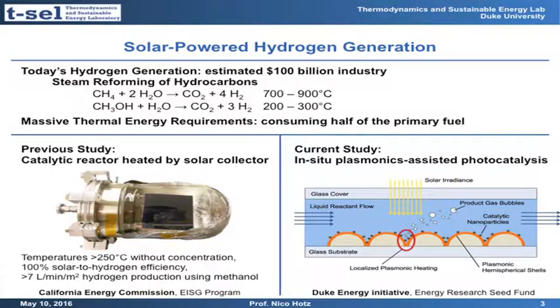And to improve that, we are looking now in a much more fundamental study, collaboration between myself and Dr. Wadin in biomedical engineering, partly funded by the Duke Energy Initiative, on how we can use plasmonic heating to heat our catalytic nanoparticles, and only those, without having to heat the entire system. So we use plasmonic substrates in this case that have a plasmonic heating in the crevice of these two hemispheres here, and we try to see if we can get enough temperature here to power methanol steam reforming, which requires at least 250 degrees Celsius. Keep in mind that the whole fuel, the whole substrate, everything is cold.